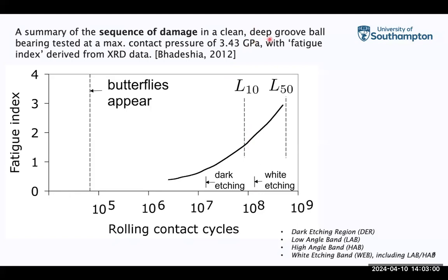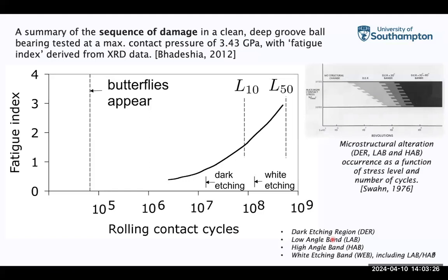These are only derived based on deep groove ball bearings and under a maximum contact pressure of 3.43 gigapascals. So of course, there are some limitations of using these data, but it gives you the general trend of what kind of phenomena may occur, or the microstructure alteration may occur during the rolling contact life. This actually agrees with Swahn's summary of the microstructure alteration, including dark etching region, low angle band and high angle band occurring in different regions of revolutions, rolling cycles.